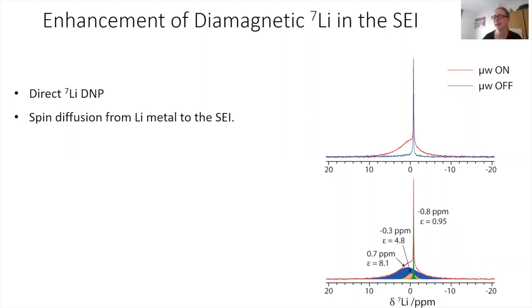So they're all packed in a glove box with an argon atmosphere, so the lithium metal shouldn't be reacting with anything. And it's not just a piece of lithium metal that you take out of a bottle or anything, because we're also worried about skin depth effects here. Microwaves and also radio frequency can't penetrate metals very far. And so what we've been looking at were these microstructures, mainly because the SEI is interesting, but also they're very thin, 100 micron diameter, if I remember correctly, so that we're less bothered by skin effects and we have more surface that we can actually work with.